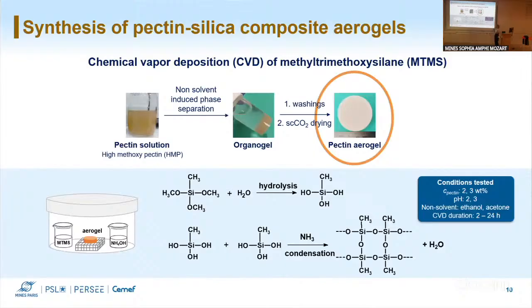All the properties of the aerogels are governed by the supercritical drying. Because we have some shrinkage during supercritical drying, we have a change in density and in pore size, we assume, and this affects thermal conductivity directly. So if we work on the organogel, we can really affect our final material a lot, which is not bad. It has a lot of potential. It has been done for cellulose. It gives good properties, but it was done the other way around. Silica has the super insulating properties and structure, and cellulose was the reinforcement network for the mechanical properties. So modifying inside the pores is feasible from the literature, but we haven't tried it.